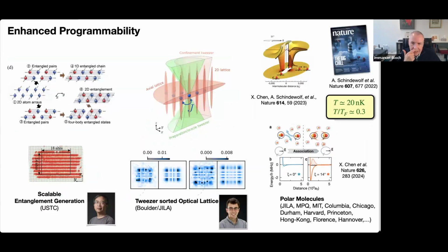And I think one particularly interesting direction, which comes to the question that was asked, is combining optical lattices with tweezers. You might have heard about tweezer arrays, where you trap individual atoms in focused tweezer beams, and then you can move these tweezers around. That works very nicely, very powerful, but the distance between the tweezers is typically much larger than the spacing of atoms in an optical lattice. And that means there's typically no tunneling motion of the atoms in the tweezers. So they are far apart. You can use Rydberg interactions to have them interact, but they can't really move around. And we really want the atoms also to move around to study, for example, the Hubbard physics that we have in the system. So can we think of combining these 2 worlds with each other?